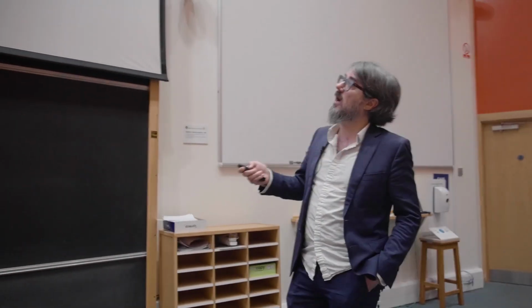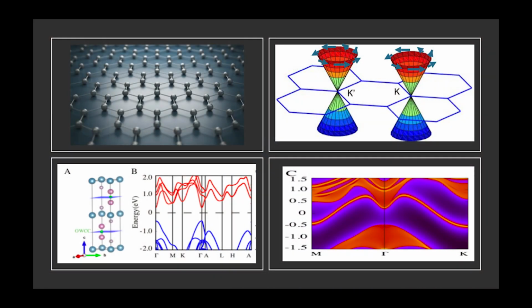Here I give you another type of material, and this material has these surface states that you can see here. This is energy versus momentum. These are bulk states, high density, but you can see surface states here. But unlike the surface states in a topological insulator, these surface states are kind of dangling. They don't connect between the upper energy manifold of states and the lower energy electron manifold of states. They're kind of dangling here. And this is really the concept of covalent bonding, which since 2010 we really understand now as just an integer property. Let me walk you through this very quickly.